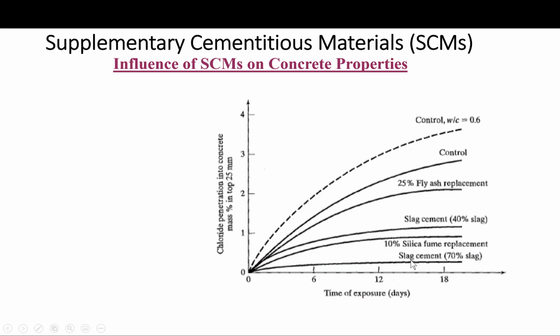This is with high replacement with slag, 70%. Replacement with slag at this much is only probably recommended in few cases. Sometimes when you need early strength, you cannot use this much replacement of slag. But in certain applications where early strength may not be important, the benefit we get in terms of durability could outweigh the other benefit.